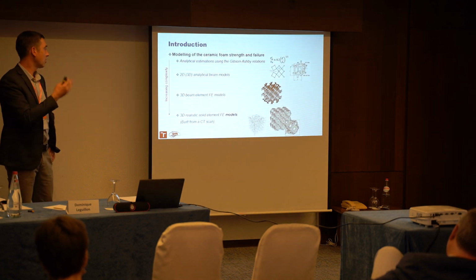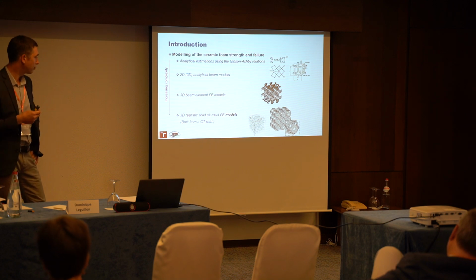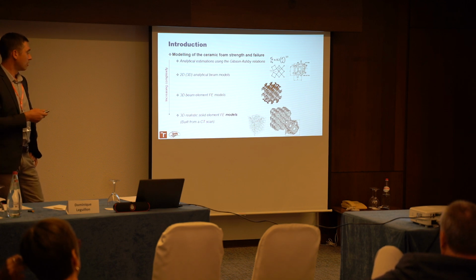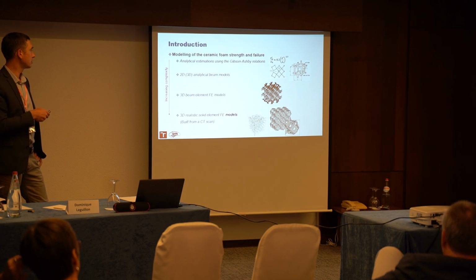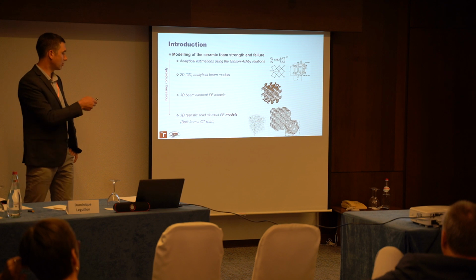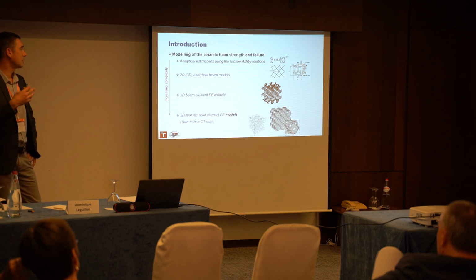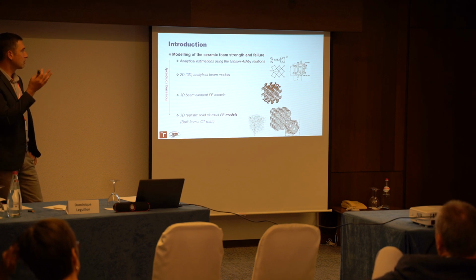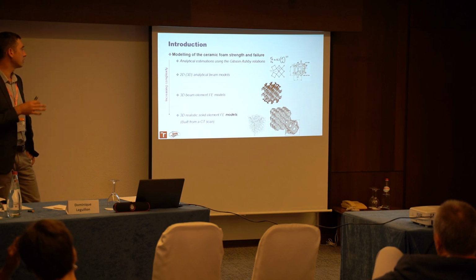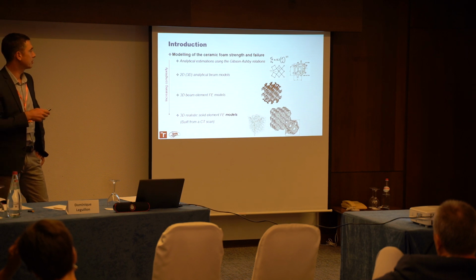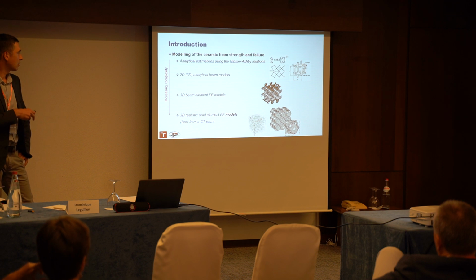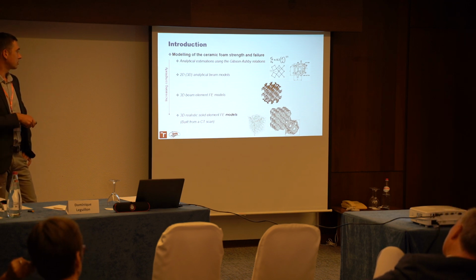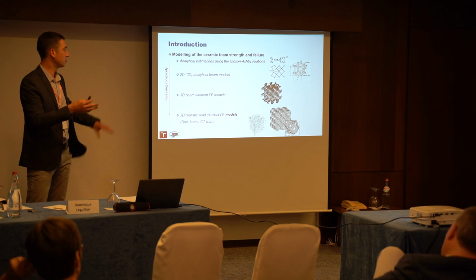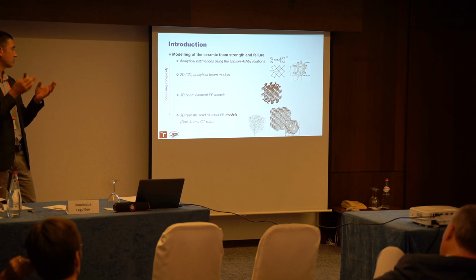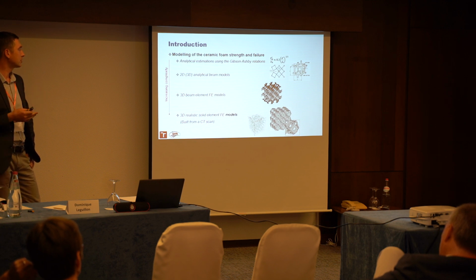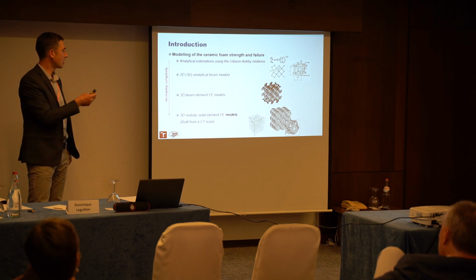there are several different approaches for how to deal with these porous ceramic materials and porous materials in general. You can estimate the strength of such foam using very simple analytical estimations from the Gibson and Ashby relations. They are based on the relative density of the foam. You can have some first estimations, so then you can use some 2D analytical beam models or 3D imaging in some specific cases to also estimate the strengths. Then what we did in the past was to use 3D beam element based finite element models, where you model the struts of the foam structure using beam elements. But this is also not very precise because you do not have a precise connection of the struts as in reality.